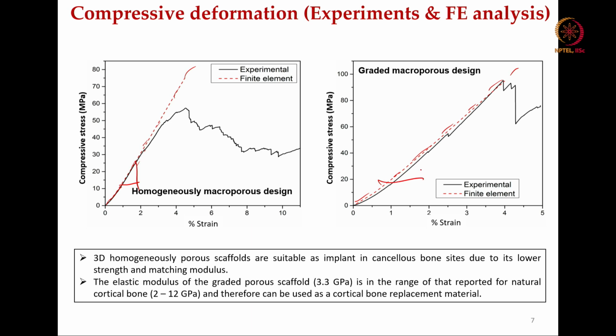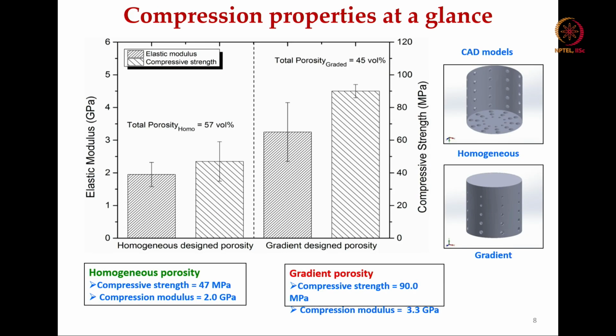That means the modulus is also very similar. The elastic modulus in the graded porous scaffolds is 3.3 gigapascal, whereas cortical bone has 2 to 12 gigapascal, and we can use it as a cortical bone replacement material. Compression properties: in case of homogeneous porosity, total porosity is around 57 volume percent, whereas in case of gradient porous